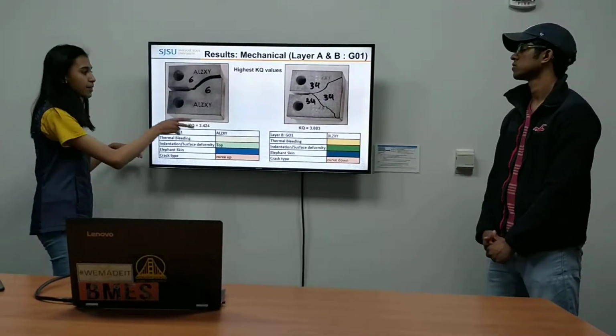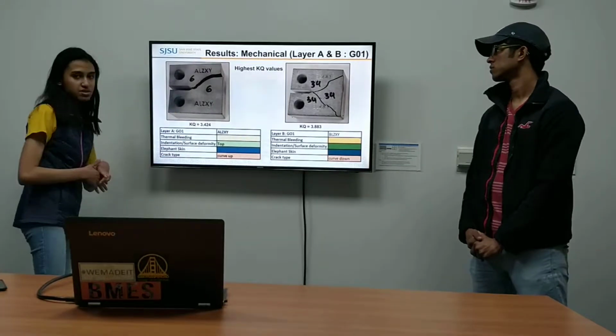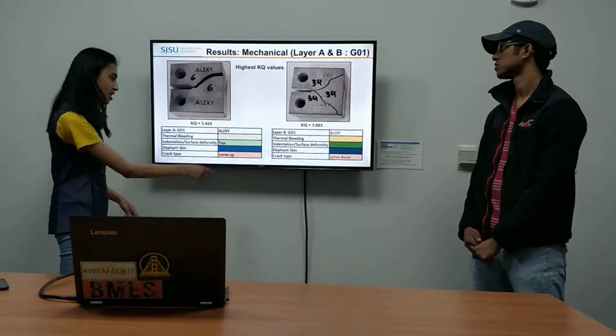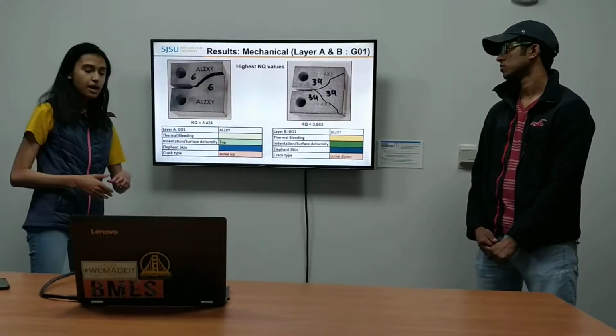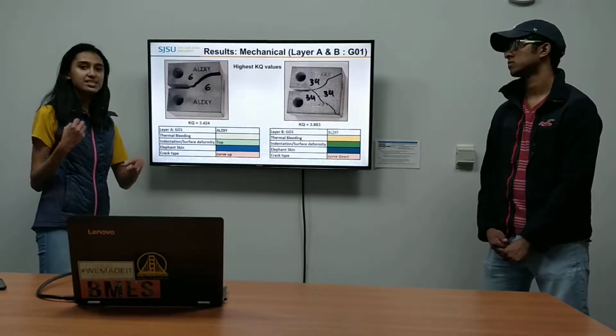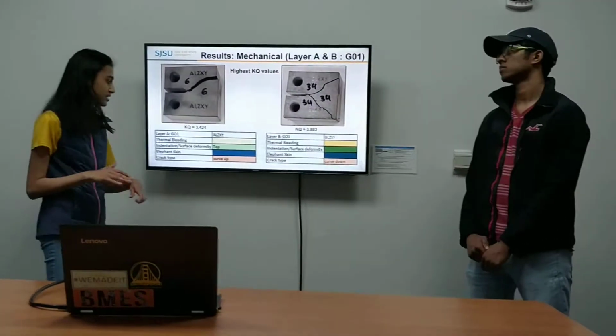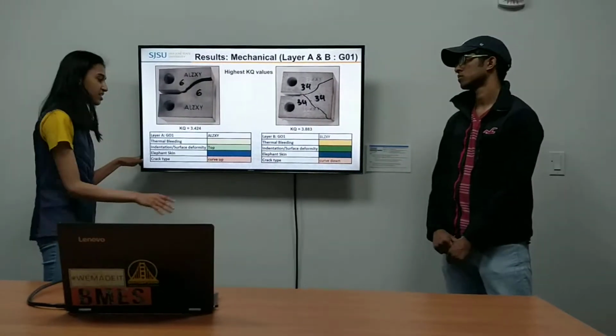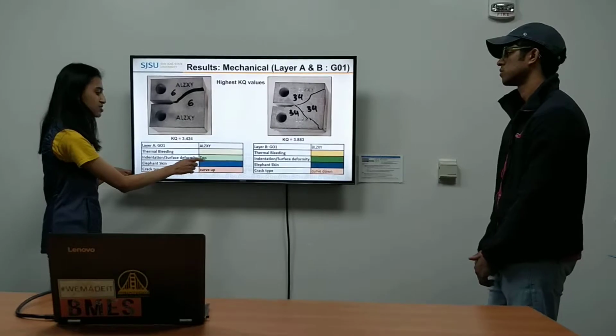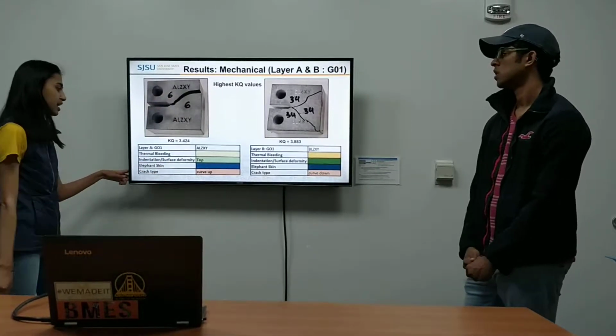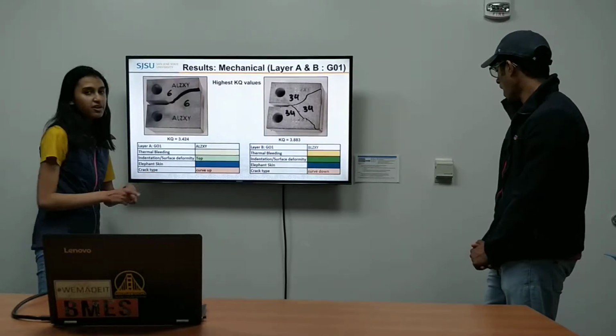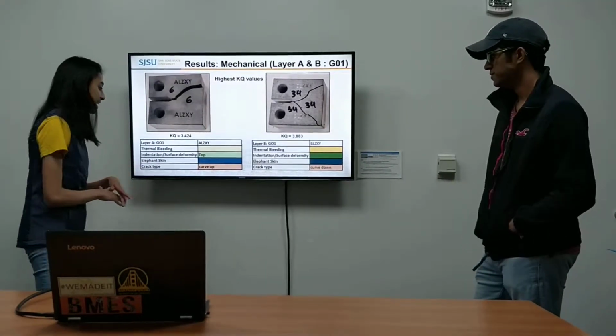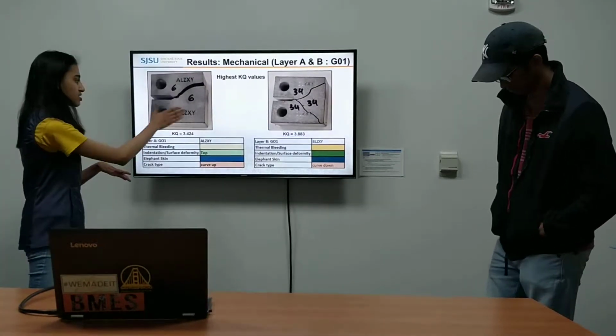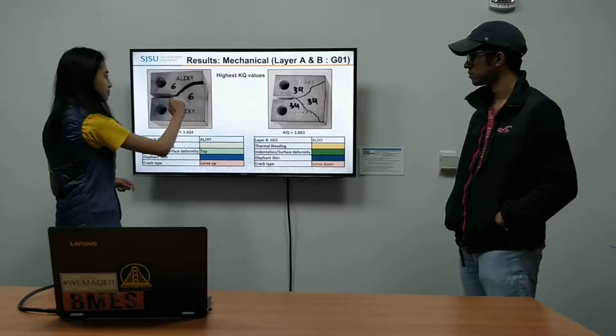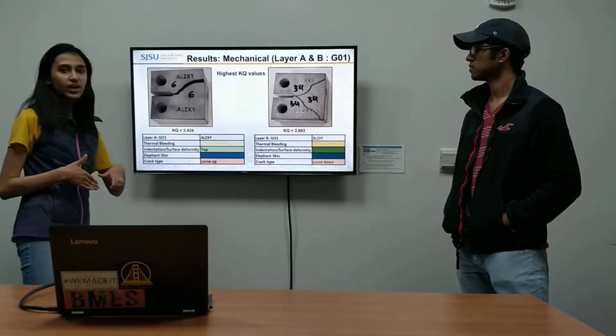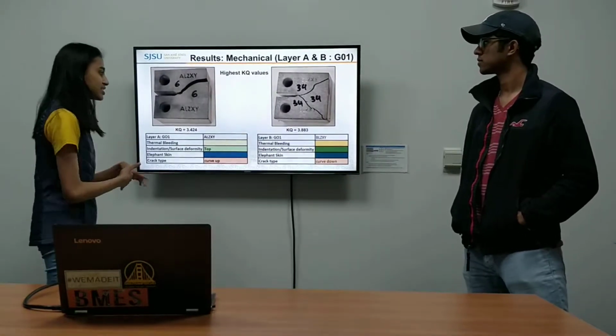But as you can see, I'm comparing the two specimens which produced the highest fracture toughness out of all the 72 samples. So ALZXY had the least thermal bleeding. What is thermal bleeding is basically how much heat is applied to the sample while it's printed on the print bed. So as you can see, this represents the lightest color, which means it has the least thermal bleeding. And there was a small indentation on the top of the specimen, and this blue color represents no, which means we did not observe any elephant skin, which is the rough skin which we find on the surface of our specimen. And as you can see, the crack type is curved up. So that's how we defined all our 72 samples by conducting visual inspections.